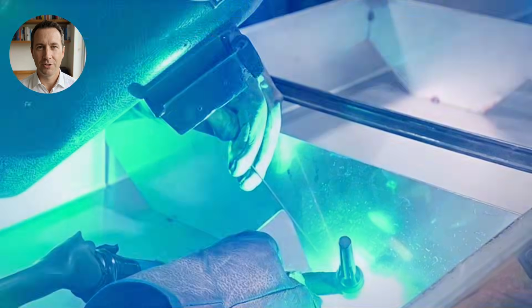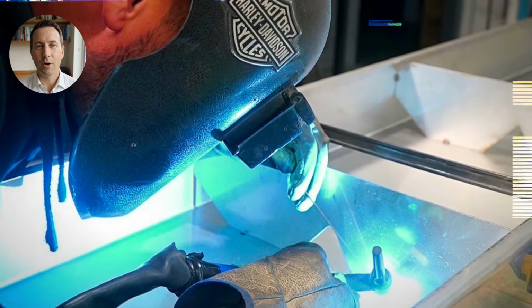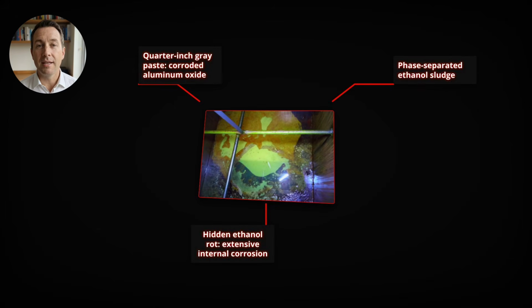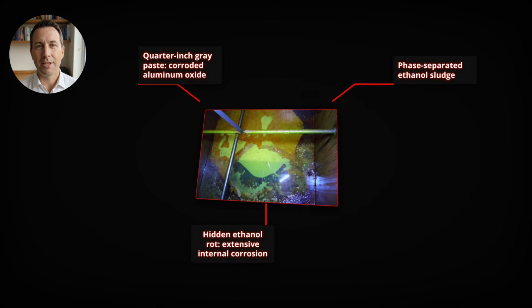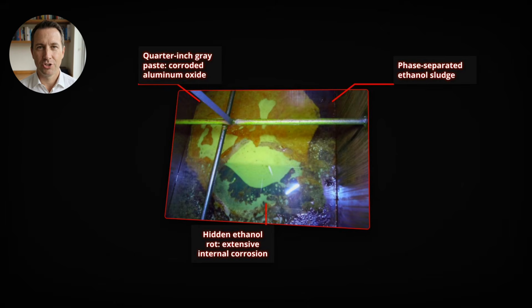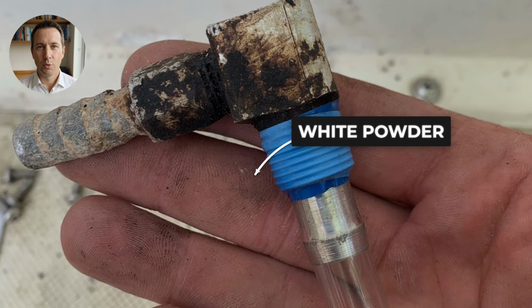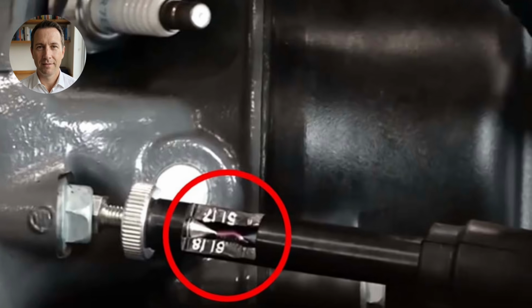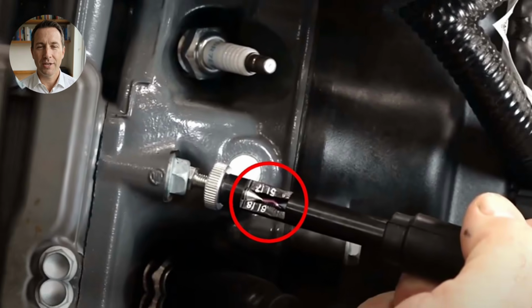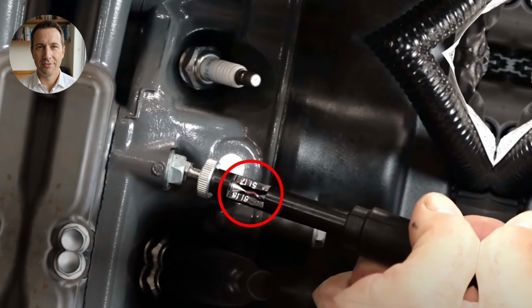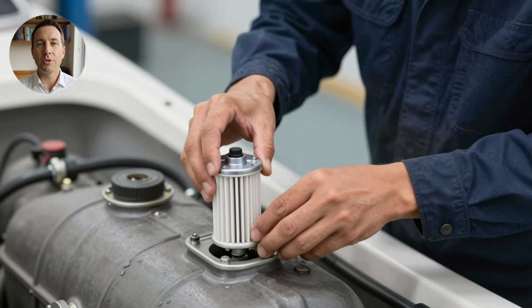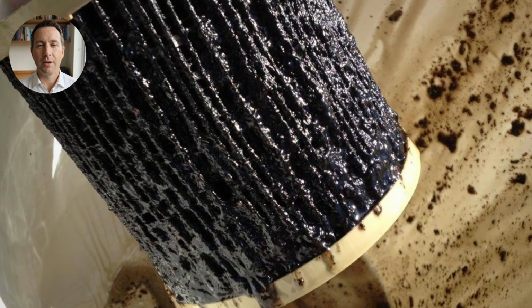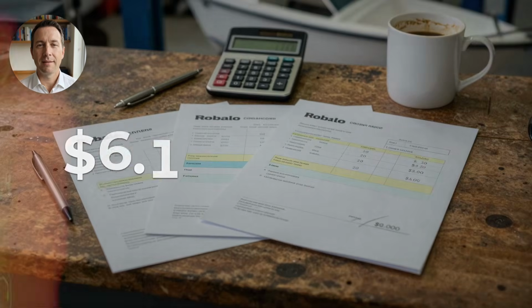inside for 3 years. When the mechanic cut that tank open on the shop floor, the bottom was coated in a 1/4 inch of gray paste, corroded aluminum oxide mixed with phase-separated ethanol sludge. The pickup tube had a ring of white powder caked around the fitting. 2 of the 6 fuel injectors on the Yamaha 250 were completely fouled. The Racor fuel filter, changed just 80 hours earlier, looked like it had been dipped in mud.